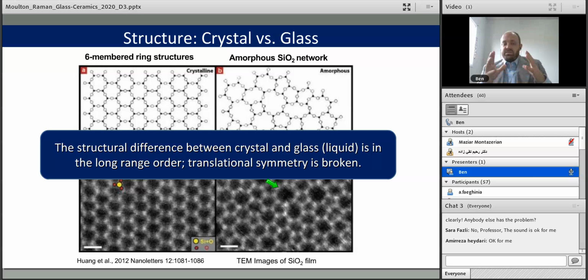So the first thing I want people to take away is that the main structural difference is not in the small silicon oxygen tetrahedral units here, but in the long-range order. What it means is that the translational symmetry is broken. So you still have a local short-range order or local symmetry, but you don't have the long-range symmetry present in crystals.